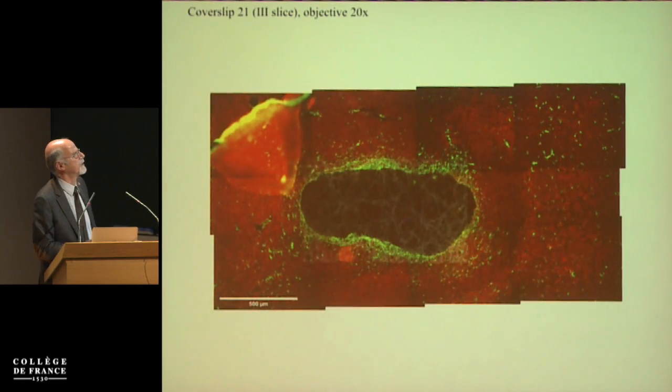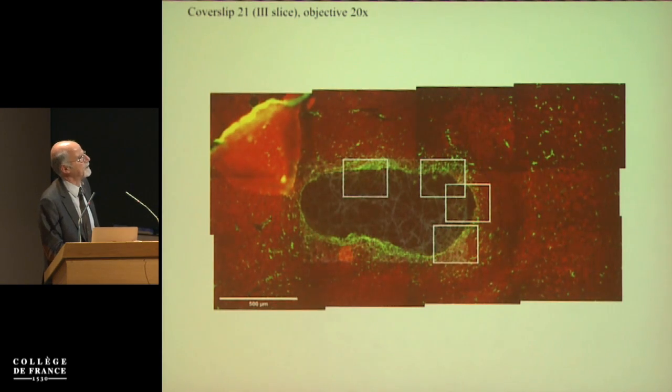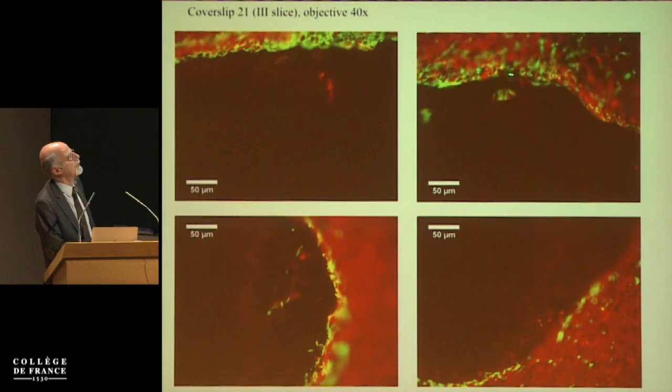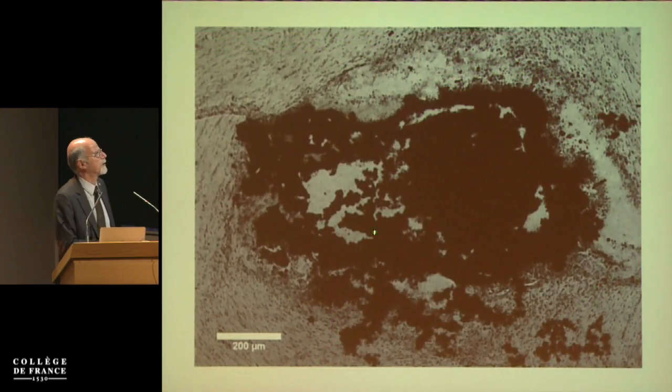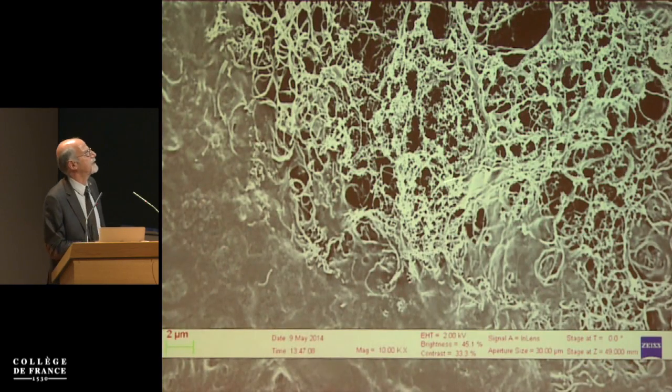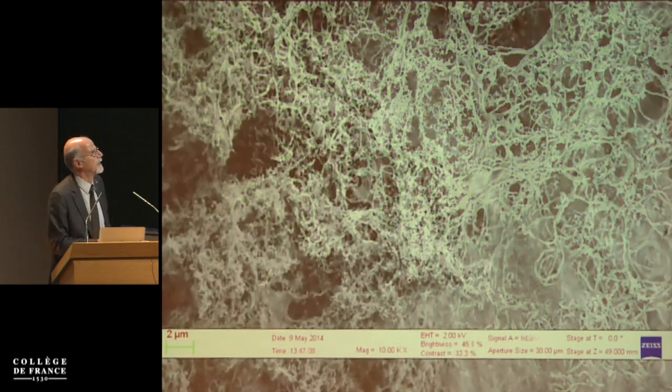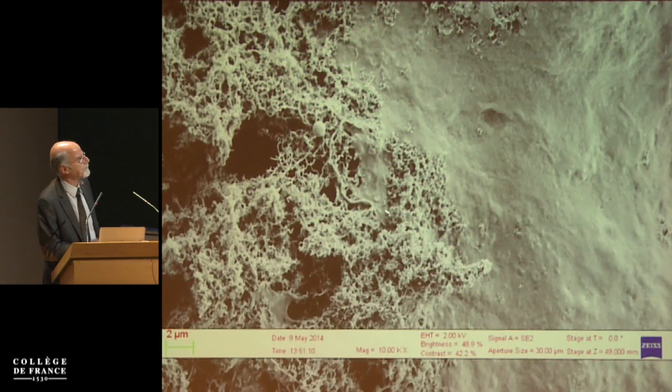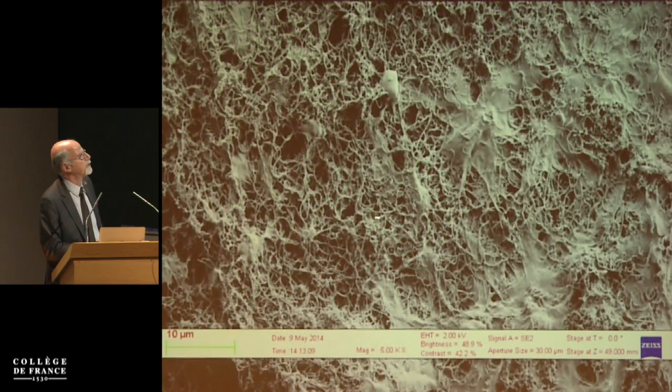Again, we can enlarge the images and see in these places what happens. And you can see that there is a very, very thin layer of scars in all these images. What is important also is that the sponge has been completely colonized by the nerve system, and the nerves have elongated inside the sponge. You can see it also from here. These are the nanotubes, and this is the living matter which is proceeding, and it's very well integrated. You can see it's completely melted with the carbon nanotube sponge, as you can see also here.